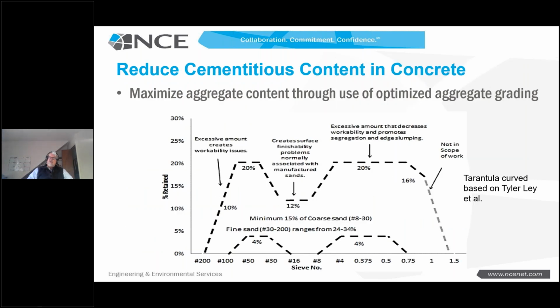So what can we do today in a practical sense? One thing is to use a low clinker cement. The second part is to use less cement. And the best way to use less cement is to put more aggregates in our concrete. There's been some excellent work done by a number of researchers. This shows something called the tarantula curve by Tyler Ley and his group at Oklahoma State University. It's one way to proportion aggregates. This is for a paving mixture, but he also has another curve for pumpable mixes.